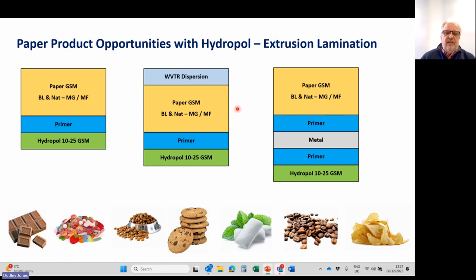If you want WVTR, we have a customer who's taken the base sheets, extrusion coated onto the paper. They've then printed and applied a WVTR dispersion coating on the top. And that got them to a WVTR of, I think it was around about 10 to 12 at 50. So again, some form of WVTR. And this product actually was the one that achieved OPRL status. What you can also do is take a metallized paper and apply Hydropol. That gives you WVTR, OTR less than 1. So again, different ways of combining materials.